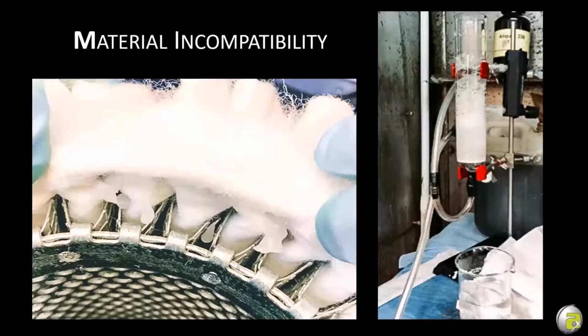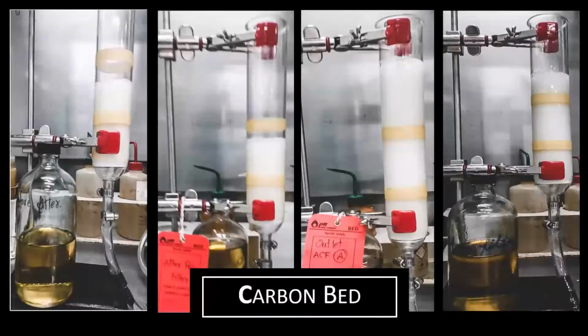The vendor said the reason it's foaming is because our filters are so effective, they're pulling out your anti-foam, but really it was the filters themselves that caused the foaming. And this is a case of bad carbon causing foaming.